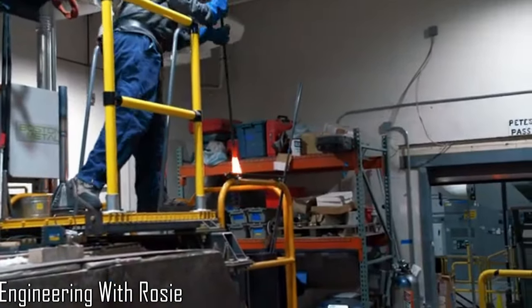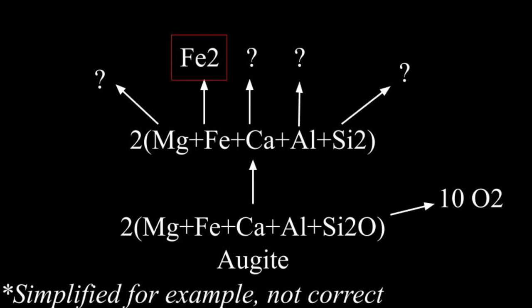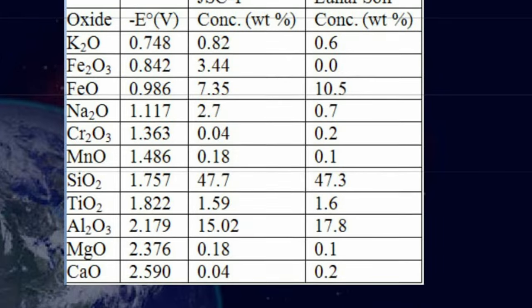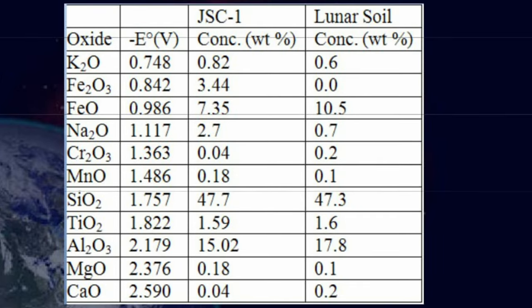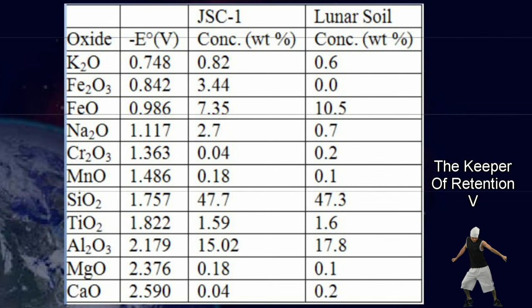So we need to not only separate the metals from their oxygen, but also from each other, and this can be done in electrolysis by varying the voltage ever so slightly. Here is a chart showing the decomposition potentials of our various regolith oxides. Each oxide has a corresponding voltage. So, very roughly, if you set the voltage potential between the electrodes to 0.8 volts, then it will decompose the potassium oxide, and reduced potassium will deposit on the cathode.